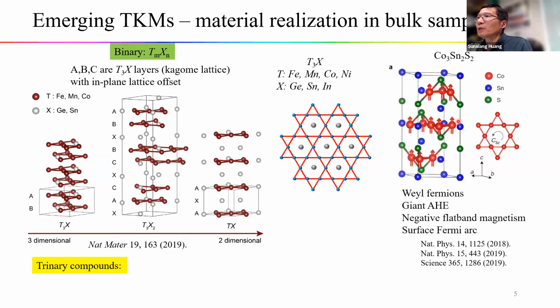We may also insert more atoms for the separation, in the case of the cobalt-3, tin-2, sulfide-2. So in addition to the separation of the tin, there is additional separation of the sulfide layer. It's probably because of the relatively large separation between them that many unusual physics have been observed in these compounds.